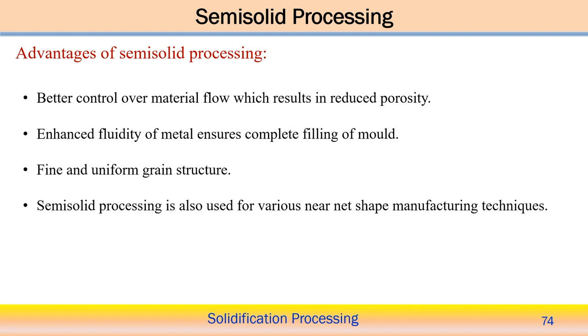Second, the enhanced fluidity of the metal ensures complete filling of the mold. The slurry can reach every corner of the mold, because the grain size is very small. The enhanced fluidity is there because a fine grain structure is achieved, and we are diverting the mixture of solid and liquid into the mold. The interface between the mold wall and the semi-solid component is also important, so that the interface resistance is not large for the semi-solid component entering the mold cavity. So this is another advantage: complete filling of the mold is possible by producing the semi-solid.